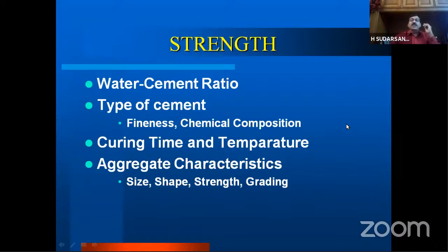And if you look at the strength aspects, you know, the strength is inversely proportional to water cement ratio. So it is always better to use very low water cement ratio to get good performance, high strength. And if you look up the types of cements, the fineness of the cement, the chemical composition of the cement, these are very important. What type of cement you have to choose for high performance concrete, and how much curing time is required and what temperature we need to maintain during the curing. These all affect the strength of the concrete.